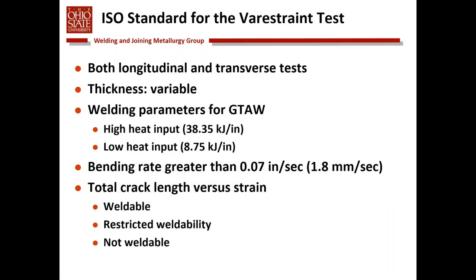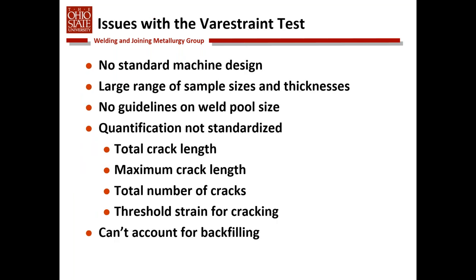Okay, there is an ISO standard for the Varestraint test. This was basically developed by the Germans. It is a reasonable standard, but there are certain things it does not consider. And frankly, we don't use this standard at OSU, primarily because its method of quantification is total crack length, which I don't believe is a reasonable measure of susceptibility. The example I give is, if your total crack length is 2 millimeters, you could have one 2-millimeter crack or twenty 0.1-millimeter cracks. Well, I guarantee you from a weldability standpoint, you'd prefer cracks that are 0.1 millimeter rather than one crack that's 2 millimeters. So I don't think the total crack length measure is appropriate.